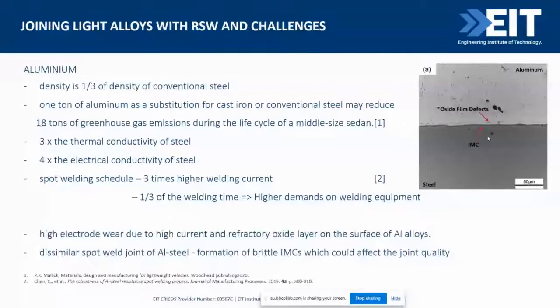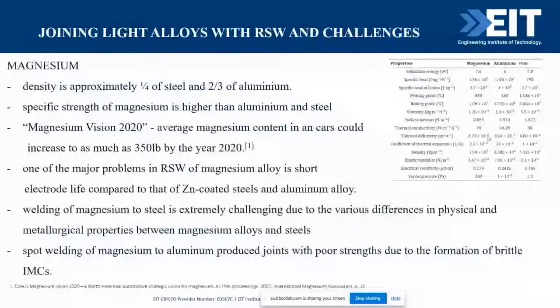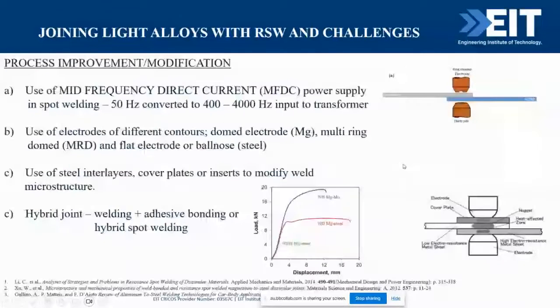They will reduce the life of the electrode. Aluminium, obviously, not that much, but magnesium is quite bad in that respect, because when you weld it, the copper electrode can easily stick to the magnesium, creating damage to the electrode. So these are the typical problems that we are seeing with resistance spot welding of magnesium as well as aluminium. All right. Now, how do we improve this?